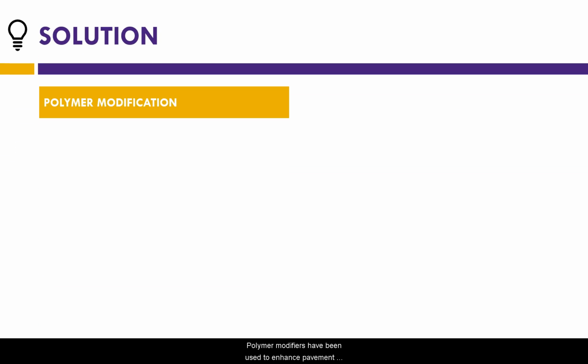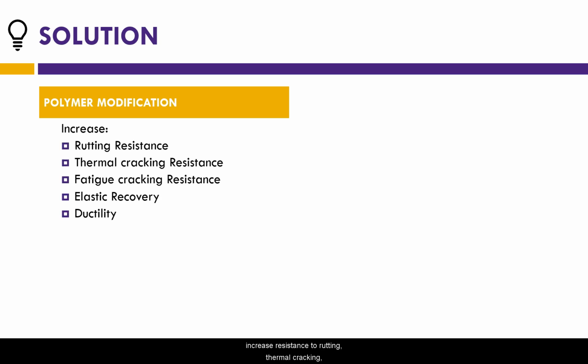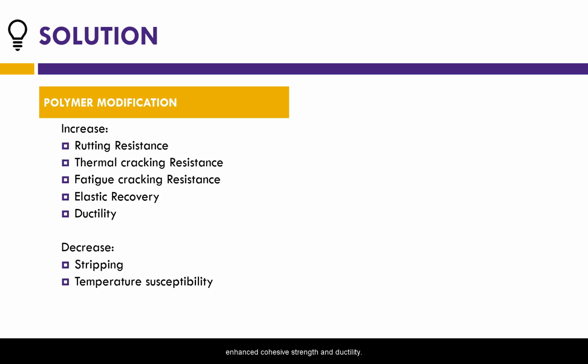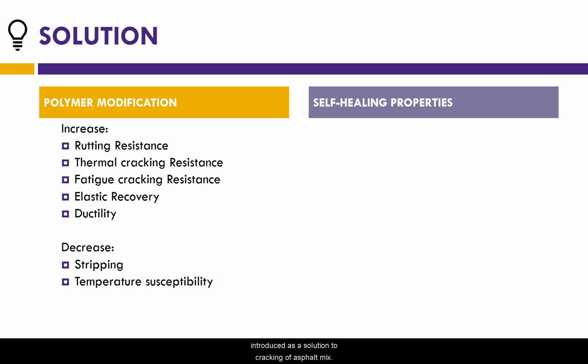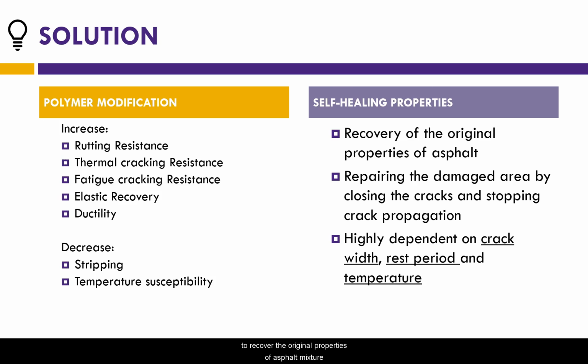Polymer modifiers have been used to enhance pavement performance and prolong its service life. Polymer modified binders have often been used to increase resistance to rutting, thermal cracking, fatigue, and to decrease stripping and temperature susceptibility. The use of polymers can also lead to greater elastic recovery, higher softening point, enhanced cohesive strength, and ductility. On the other hand, the concept of self-healing was introduced as a solution to cracking of asphalt mixture. Self-healing properties of asphalt may be defined as the ability to recover the original properties of the asphalt mixture by closing cracks and stopping crack propagation.